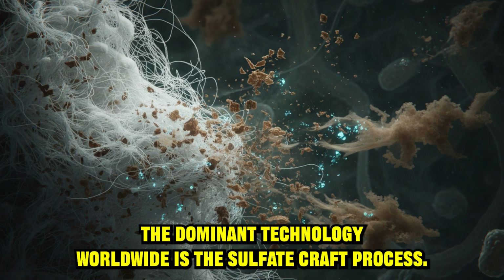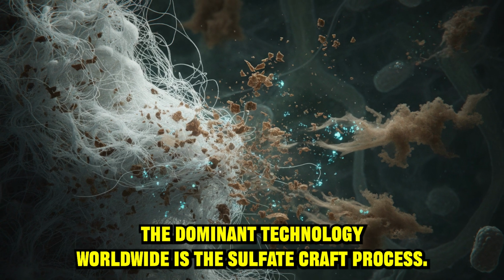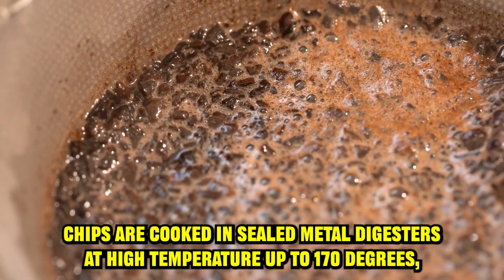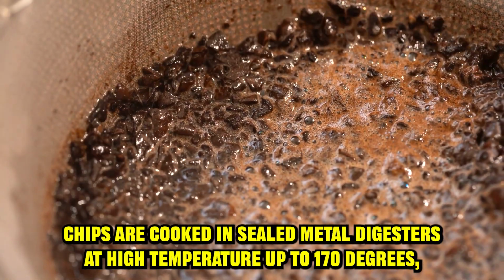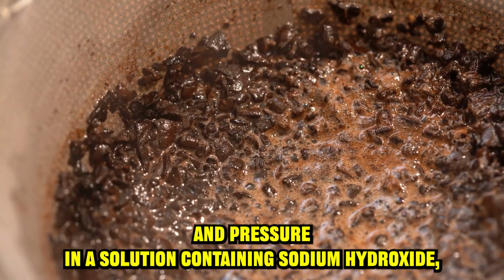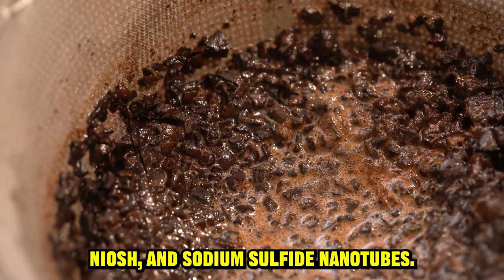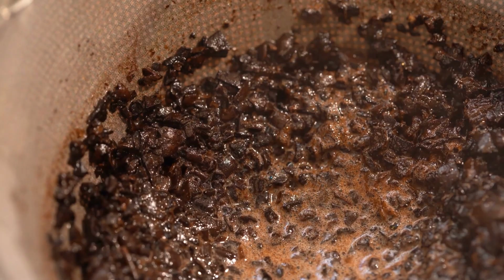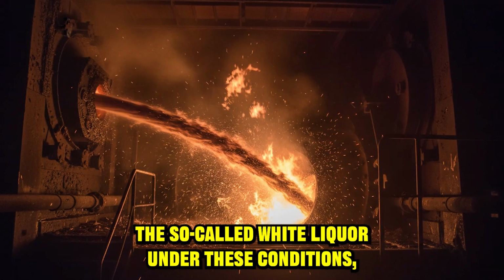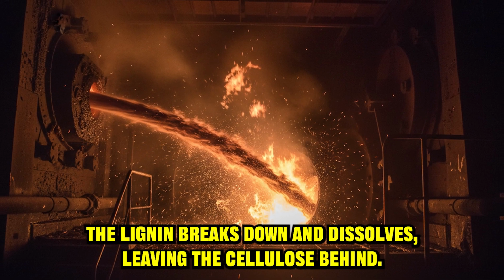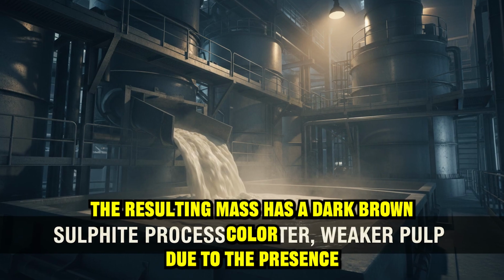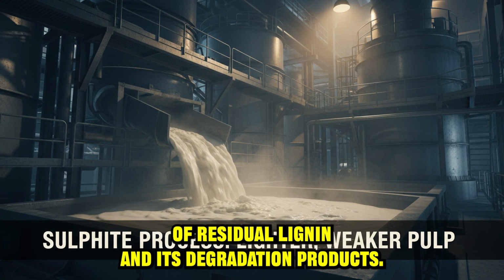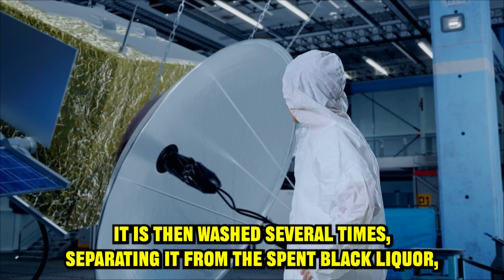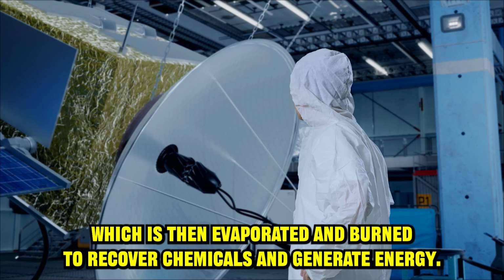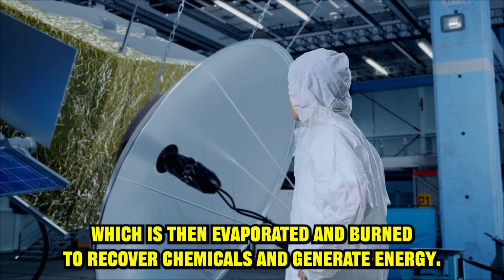The dominant technology worldwide is the sulfate kraft process. Chips are cooked in sealed metal digesters at high temperature, up to 170 degrees, and pressure in a solution containing sodium hydroxide, NaOH, and sodium sulfide, Na2S, the so-called white liquor. Under these conditions, the lignin breaks down and dissolves, leaving the cellulose behind. The resulting mass has a dark brown color due to the presence of residual lignin and its degradation products. It is then washed several times, separating it from the spent black liquor, which is then evaporated and burned to recover chemicals and generate energy.